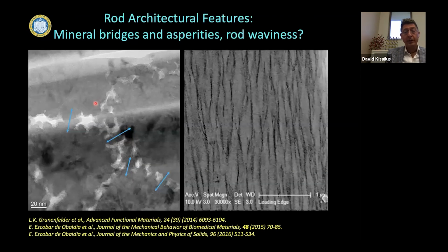We've also found, this is now another transverse section of this region where you'd see one nanorod, another nanorod, a third, and a fourth, where the nanorods are not quite smooth at their interface, they're quite rough, and they have what are called nanoasperities. And some of these nanoasperities or bumps are actually bridged between each other, one rod to another, forming a mineral bridge. And we also see a little bit of localized waviness in these nanorods.